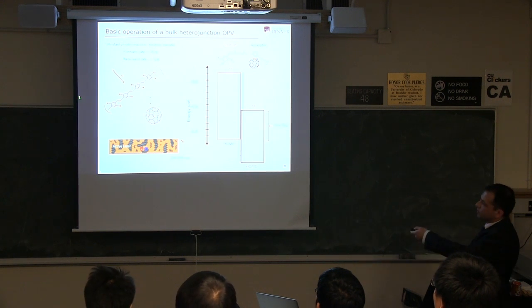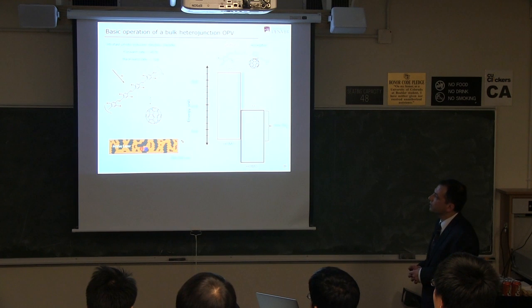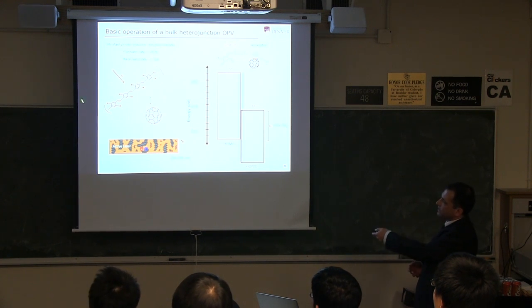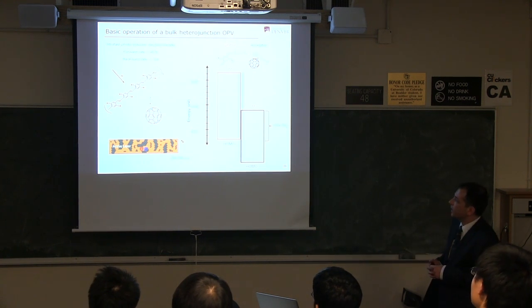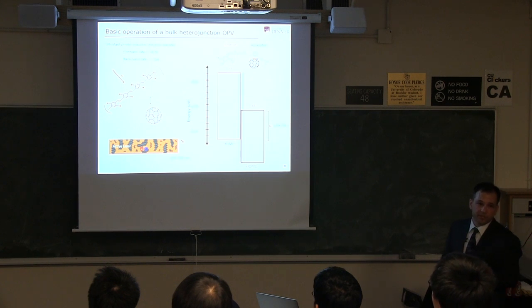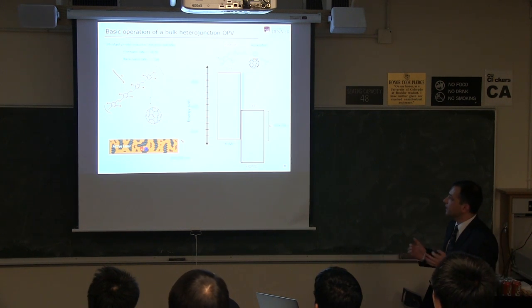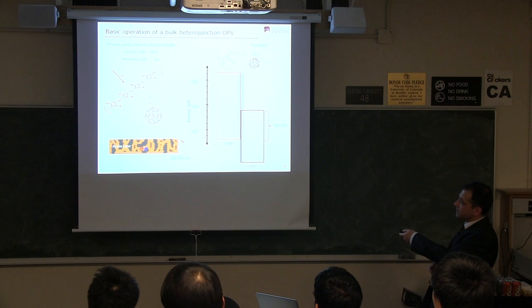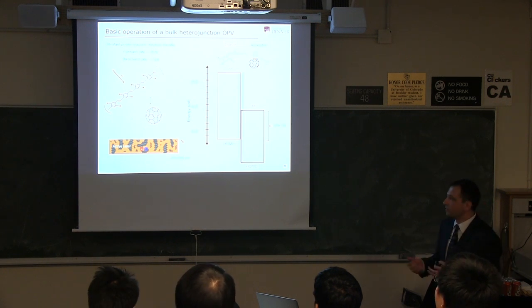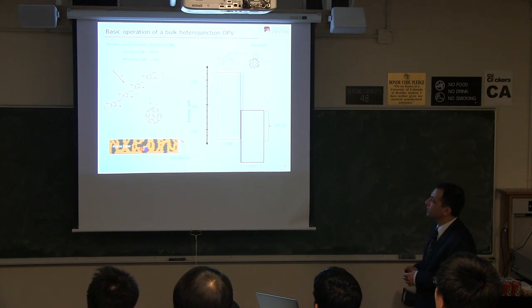This is a pi conjugated segment, typically 4 to 7 monomers long. There's an exciton that's formed in that segment. That's the excited state, and that lives typically a couple hundred picoseconds, 300 picoseconds. Now what happens is if there's a C60 in the vicinity, being a few nanometers or 1 nanometer, there's an